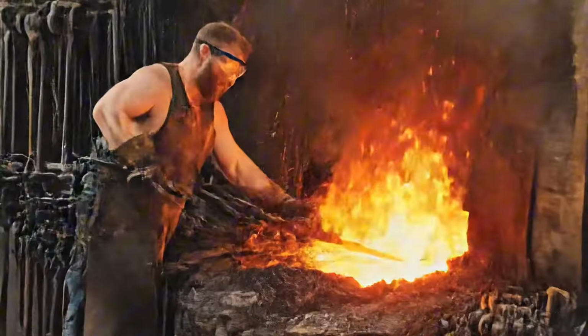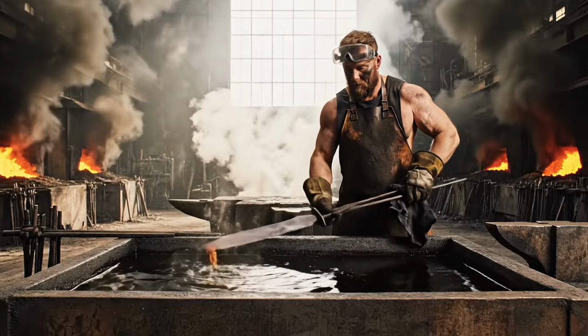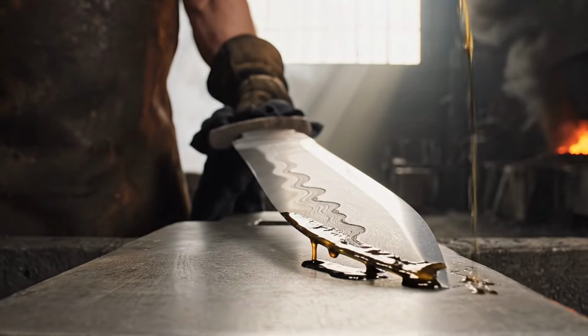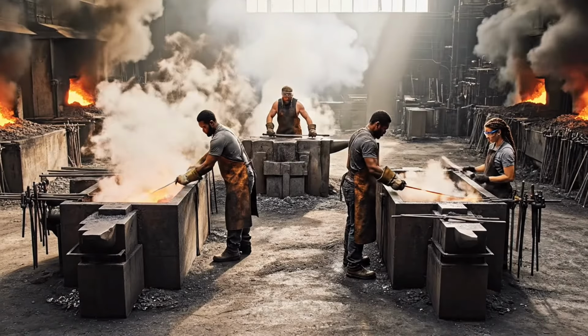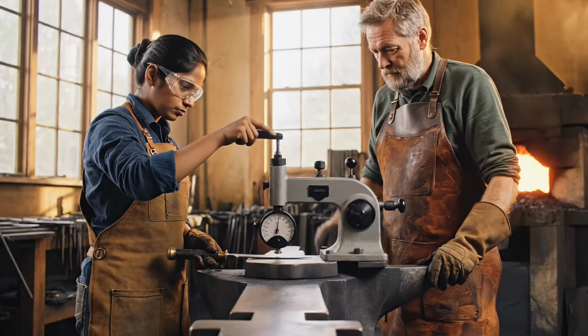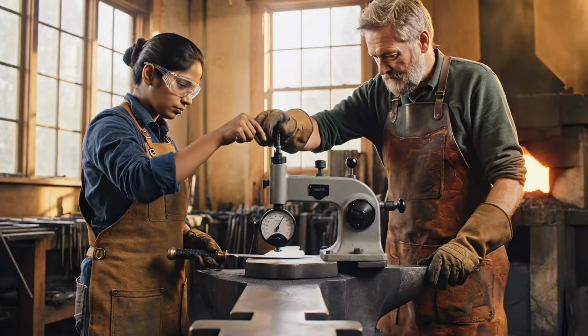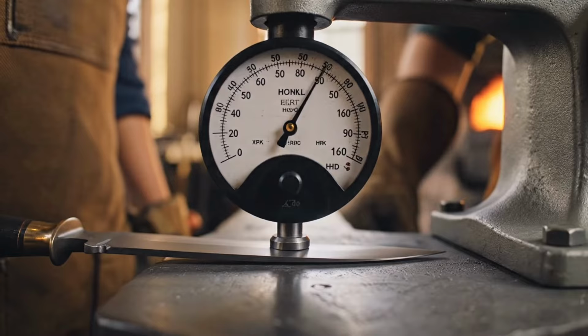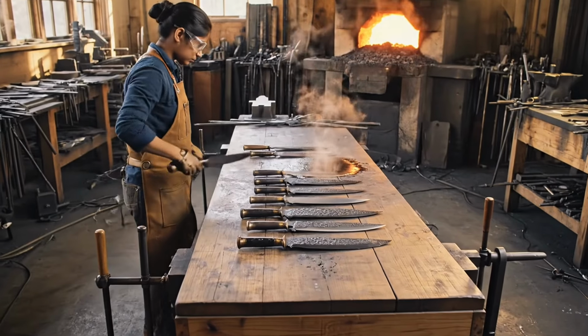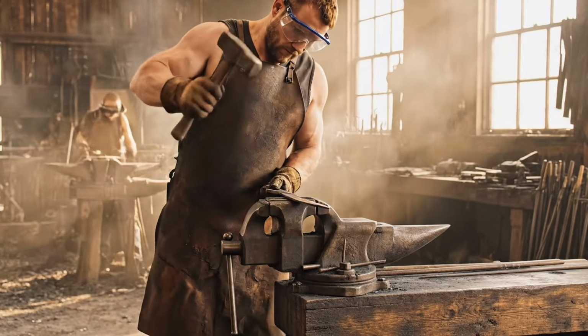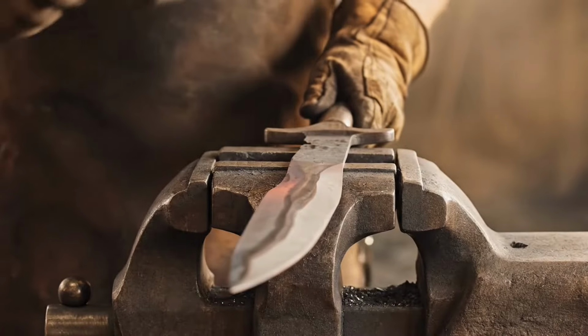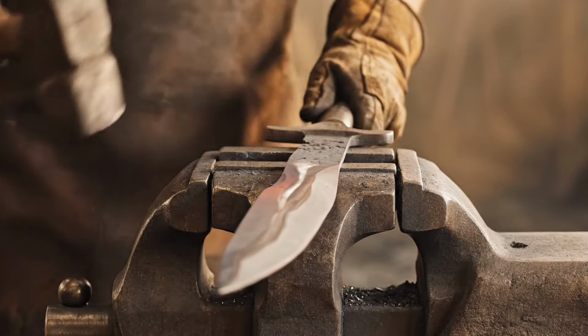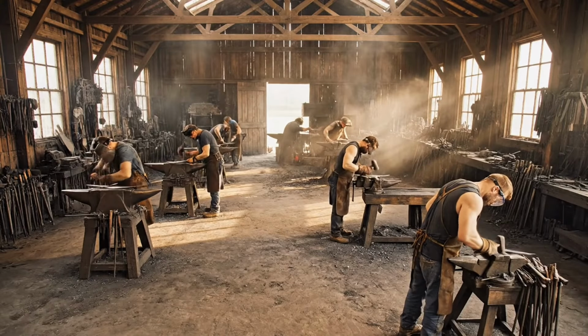rapid quenching. Freshly quenched, the blade is cleaned and inspected for warping or stress fractures caused by the sudden temperature drop. After quenching, the blade's hardness is measured to ensure it reached the required structural strength for a forged knife. If any warping occurred during quenching, the smith straightens the blade while it is still relatively stress responsive.